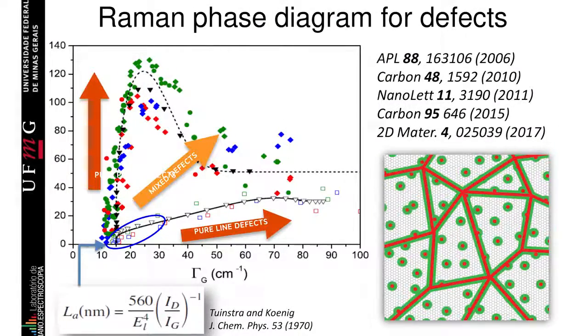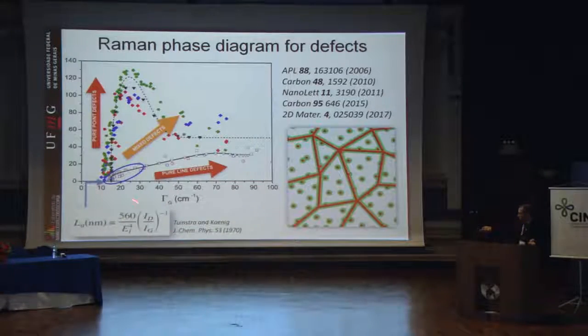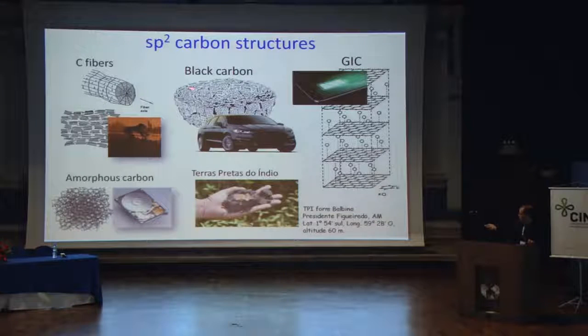And we developed a methodology based fully on Raman spectroscopy. Here is the ratio between the D and G peaks that is usually studied, is like this. And this is the width of the peaks, okay, one of them. And you generate a phase diagram that, if you have points on this place, it means you have only grain boundaries. If you have points here, it means you have point defects. And if you have anything in the middle, you have a sample like this. So when you develop this kind of thing, you can understand very well the material you are dealing with. And this has been applied in many